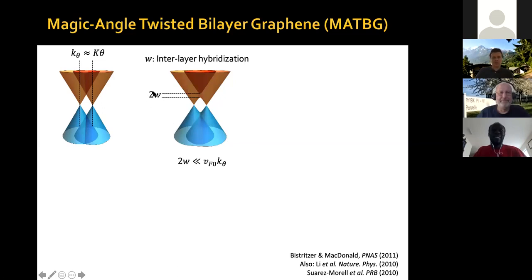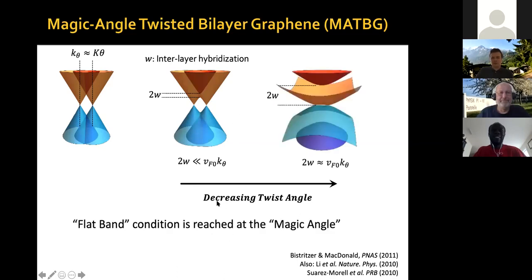This is the situation when the interlayer hybridization is much smaller than the energy of this crossing point. But as you twist, as you decrease the twist angle, this gap goes lower and lower and lower until the bottom part leads to a flat band condition. And that flat band condition is reached at the magic angle, which is about 1.1 degrees. And this magic angle was coined by Bistritzer and MacDonald, and there were earlier STM works and also some other calculations predicting the existence of these flat bands, as I mentioned yesterday in more detail.